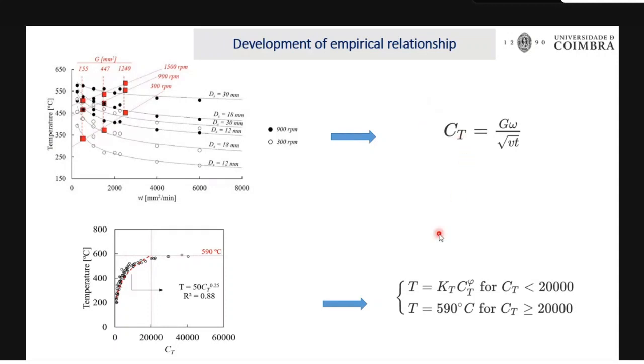But this is not sufficient to predict the final temperature. So what I did is plot this CT against the temperature for different values, and I found that 590 is a threshold; after 590 and 20,000 you could not go higher, which means this temperature is the maximum solid state temperature friction stir welding can achieve. In this way, the curve fitting happens here, and with the curve fitting, the equation is derived. Don't get confused about the curve fitting. If you have a straight line, the straight line equation is y equals mx plus c.